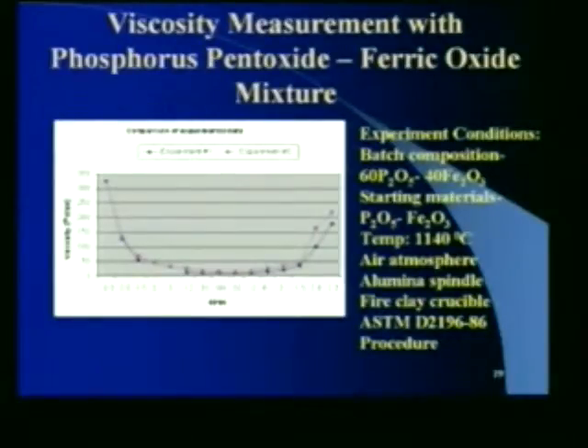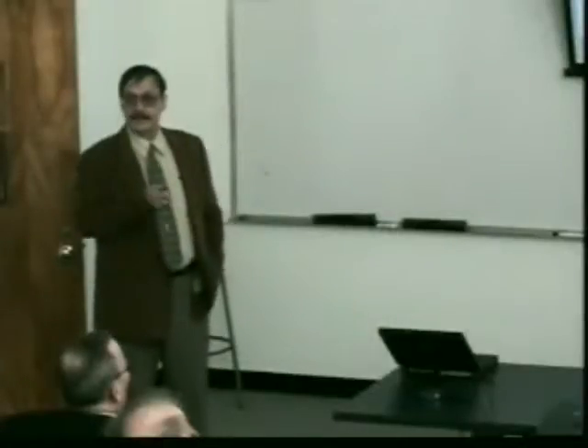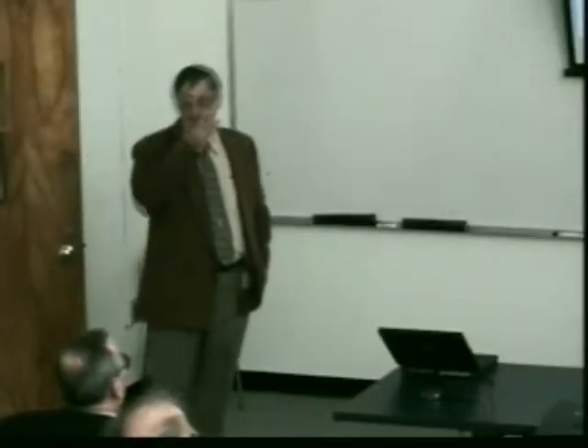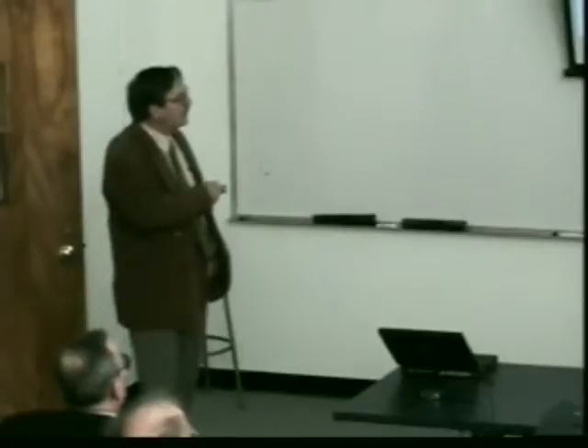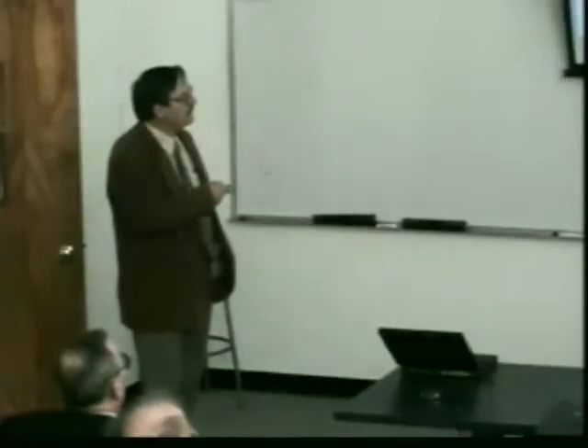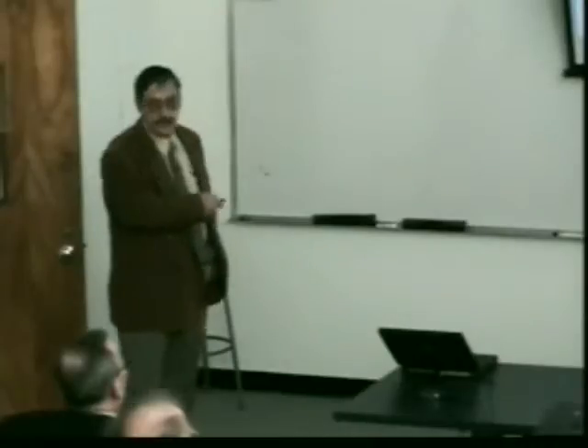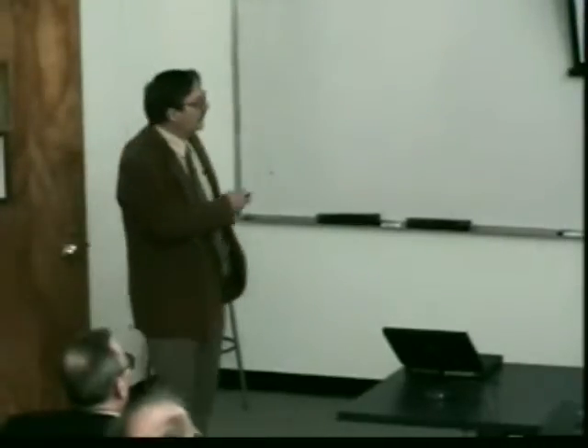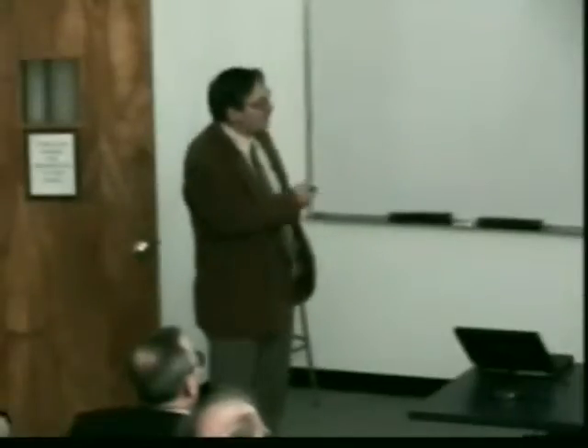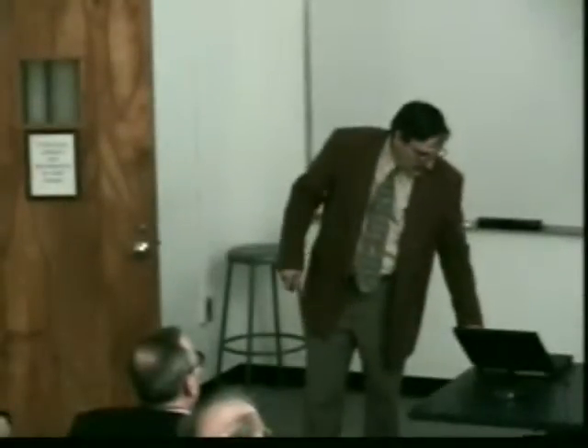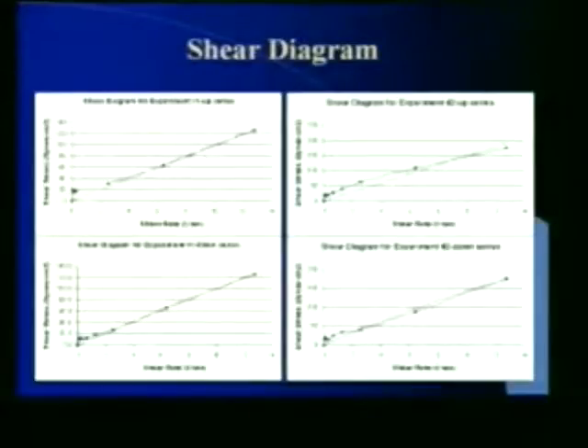So you take some, mix up 60% P2O5 and 40% Fe2O3, and you put it in the viscometer, and you start increasing the velocity of the viscometer, and the viscosity changes. Well, that's not good. We expect, as most of you know, viscosity to be constant with shear, with Newtonian fluids. And this is typical of a non-Newtonian plot, where you speed up the system and then you decrease it, and you look at how the viscosity changes during both increasing and decreasing rates of shear. So right away we see this as a non-Newtonian fluid, which from a process engineer's point of view is not a great thing.